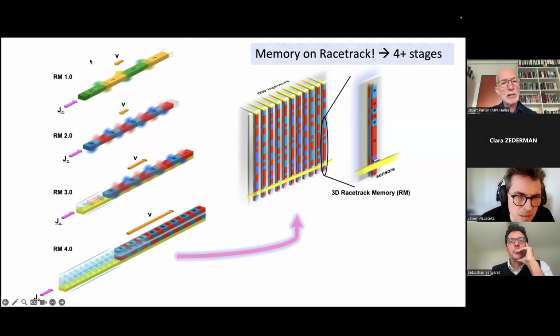And as you can see in racetrack 1 to 3, the stray fields from the domain walls are so large that they cause significant interactions between neighboring domain walls within one racetrack or the neighboring racetrack, which we showed by micromagnetic simulations. But racetrack 4.0 eliminates all the net magnetization so that there's no stray field.